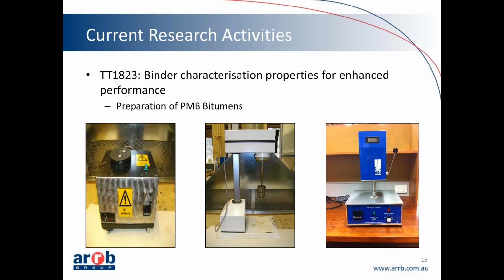Now, for this project, we wanted to have a particular type of polymer modified binder that couldn't be supplied to us. We needed roughly between 16 to 20 kilos worth of each bitumen for the bitumen testing and asphalt testing. The particular type of polymer we had to manufacture ourselves because we needed to know what we put into it. We couldn't get a commercial polymer modified binder because there are confidentiality issues in relation to what goes into manufacturing of those polymer modified bitumens. So we made them ourselves.